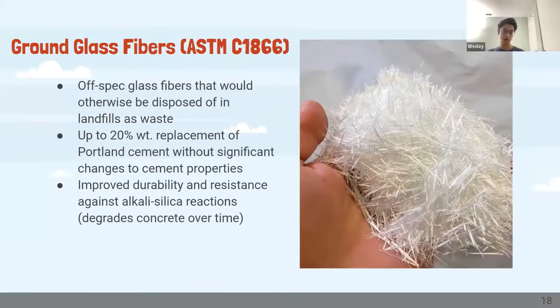Next slide. And so another type of SCM is called ground glass fibers. And this is, again, a waste material from the glass industry this time. Within the glass industry, there are a lot of high standards, and those products that don't meet the standards that the customers want are off spec, so off specifications. These would generally be disposed of in landfills. But instead, you can actually use them as an SCM. And so these can typically replace Portland cements by up to 20 weight percent.